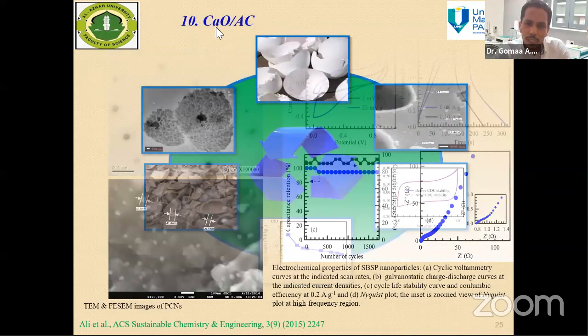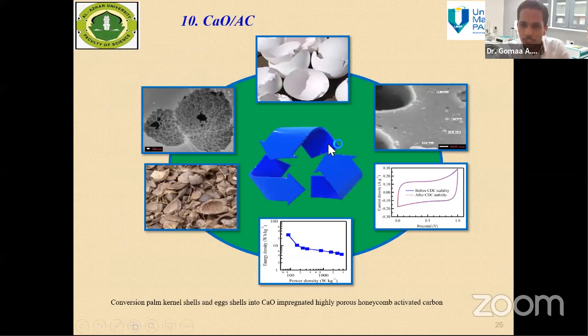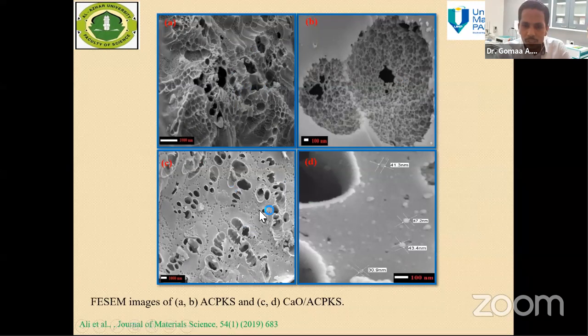And I think the last example, activated carbon, could be prepared from palm kernel shell, and it has been impregnated with calcium oxide from eggshell. So here we use two different waste precursors, which are palm kernel shells to obtain activated carbon, and eggshells to obtain calcium oxide to prepare a composite of this calcium oxide activated carbon. And here we obtain the honeycomb structure of carbon materials, a very porous structure of the activated carbon materials, and the oxide species are distributed on the surface of this carbon material.